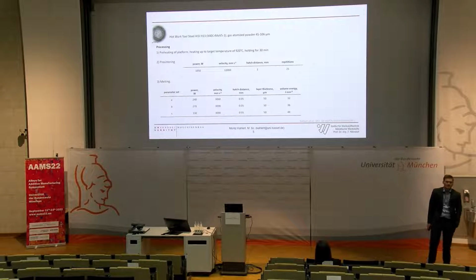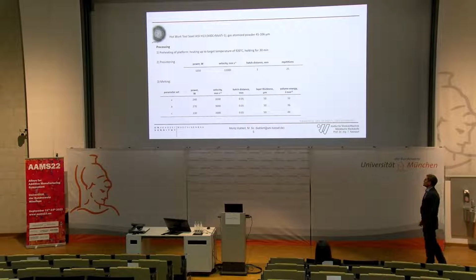In this investigation, we used powder of the steel AISI H13, in a gas atomized state with a powder size distribution of 45 to 106 micrometers. For processing, we preheat the platform to the target temperature of 920 degrees and hold it for 30 minutes, sintering the powder under the base plate to increase the electrical conductivity. In the pre-sintering process, we used these shown parameters, and for melting, we just varied the power of the beam, which results in 3 different volume energies.